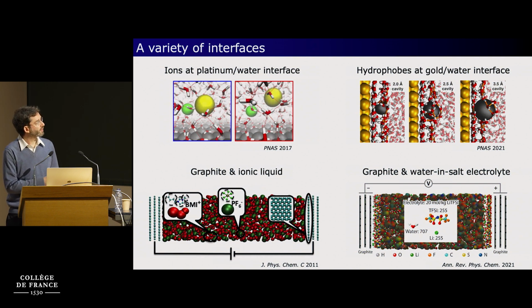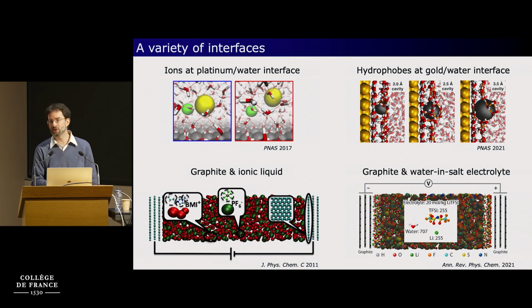In the context of energy storage, we modeled supercapacitors based on graphite electrodes with an applied potential difference, separated by, for example, ionic liquids. So this is an example that I'll get back to with butyl methyl imidazolium cations and hexafluorophosphate anions, using a coarse-grained model at the time, but now with the increase of computational resources, we can use a more elaborate model of electrolytes and model more complex electrolytes, like these water-in-salt electrolytes that are interesting in terms of energy storage because they have a wider electrochemical window.